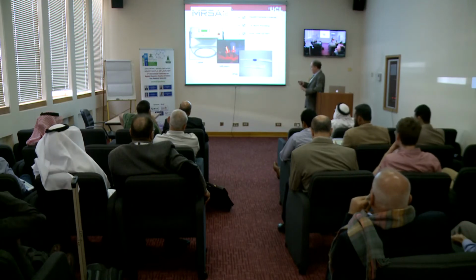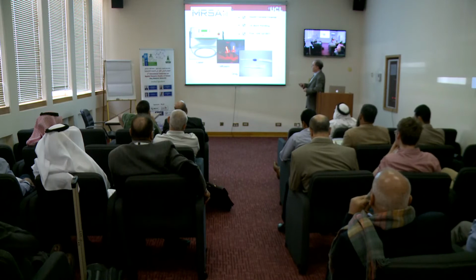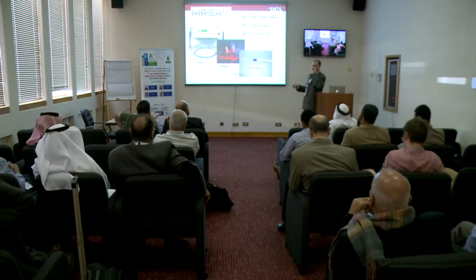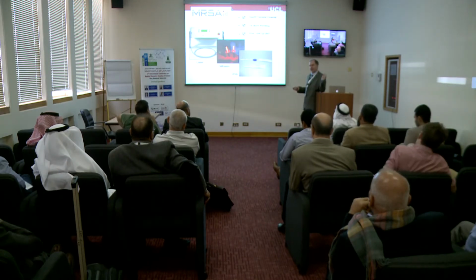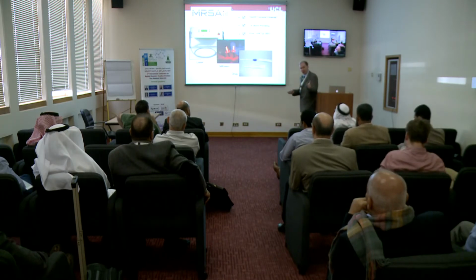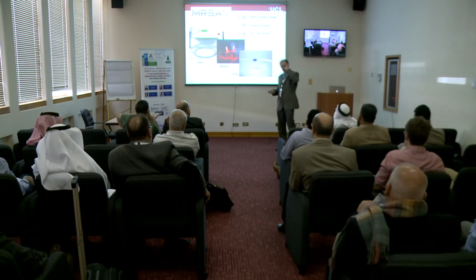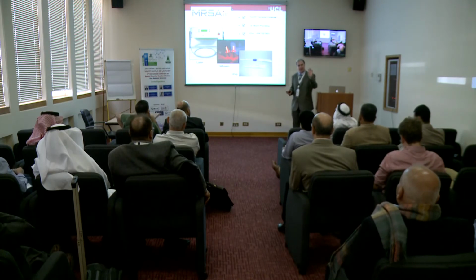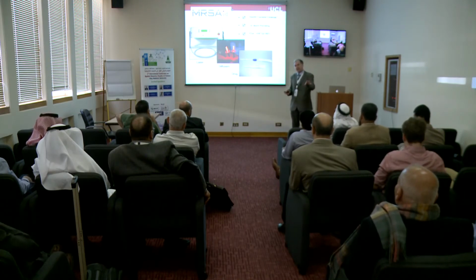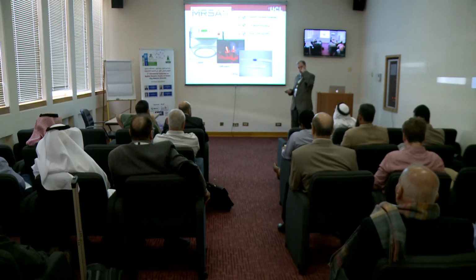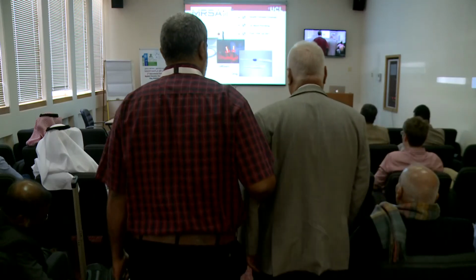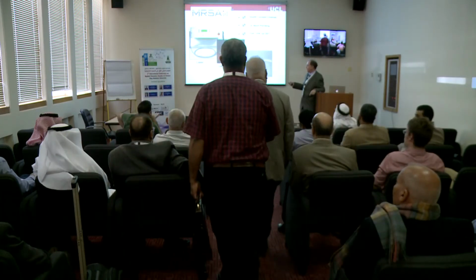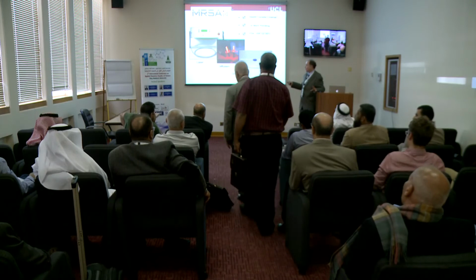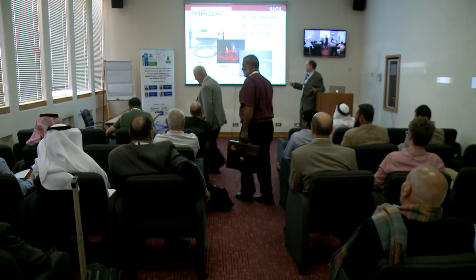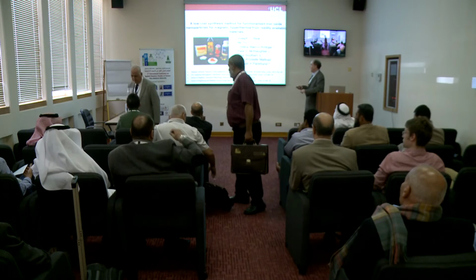We've worked together with a company called Ondyne Biopharma, and they've developed these diffusers which can be used in the nose to disinfect people prior to going to hospitals. 1 in 4 of you will have an MRSA infection in your nose. It can stay there, you're relatively healthy, but 1 in 4 people in this room will have that. It lives at the space called the anterior nares, which is between the hard and soft part of your nose. Now if you've got that and you're an immune suppression patient, that could be very dangerous in a hospital. But if you use these diffusers with this blue dye, then that can actually get around that.